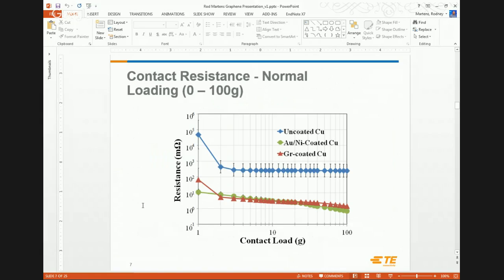On this slide, we can kind of see what happened here. So the blue curve, which is a little bit higher in terms of contact resistance, is the uncoated copper. The red would be the graphene coated copper, which is behaving somewhat similarly to our gold coated control coupon. So this is very interesting. I guess I should note that the horizontal axis is increasing load. So we start at 1 gram and then we load all the way out to 100 grams. And then monitor the resistance, as it decreases.